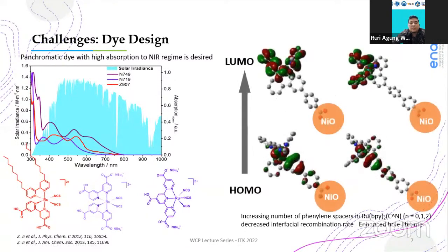Such as a ruthenium complex with dipyridophenazine, or DPPZ, ancillary ligand, which should be used as a benchmark ruthenium complex in this way, because the prevalent dye design is that the HOMO, the highest occupied molecular orbital of the dye sensitizer, should be localized on the anchoring group to overlap with the valence band orbitals of the nickel oxide, while the LUMO, the lowest unoccupied molecular orbital, extends to the distal periphery of the dye molecule away from the nickel oxide surface.